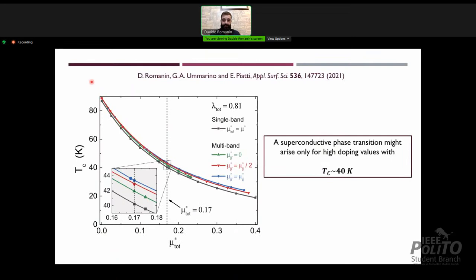Indeed, what we predicted was that at high dopings, this system could achieve a critical temperature of 40 Kelvin. However, what's the problem? This could not be seen experimentally. Indeed, up to now, the technique that we have allows us to probe the low and medium doping regime. So maybe in the future, it will be possible also to probe the high doping regime and to see if actually we could achieve 40 Kelvin of superconductive phase transition.